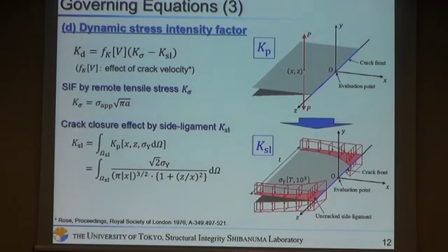The final equation is the dynamic stress intensity factor. It is noted that in this equation, the crack closure effect is considered. That is, the dynamic stress intensity factor is evaluated as a product of the correction factor of effective crack velocity and the static stress intensity factor.